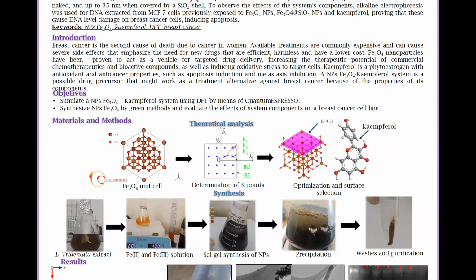All of it was carried out in closed flasks in order to prevent further oxidation of the product. These were washed with water, ethanol, and acetone until no remains of the extract were present. To add the silicon dioxide core shell, we used TEOS in alkaline environment as well as APTES in water bath. The final product was characterized by means of transmission electron microscopy at CIMAV's National Nanotechnology Center.